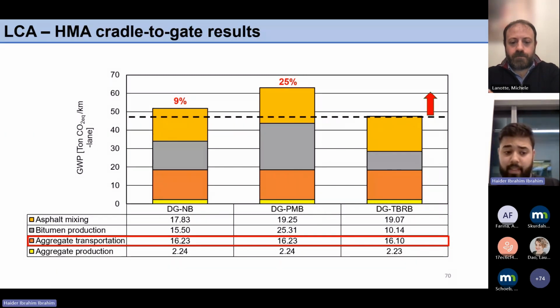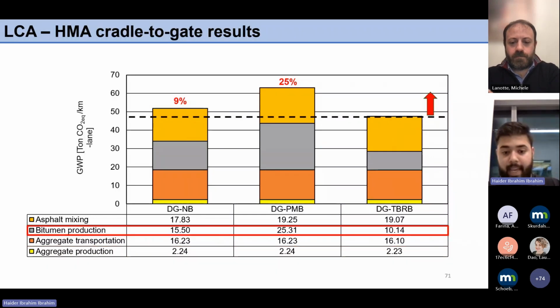The main difference created here is by the bitumen production. Starting with the DGPMB, we can see that it's much, much higher compared to the DGTBRB especially. That's owing to the fact that the SPS in the DGPMB is imported all the way from Germany through Geneva to the UAE. Plus there are added environmental burdens from the blending process of SPS with the base binder.